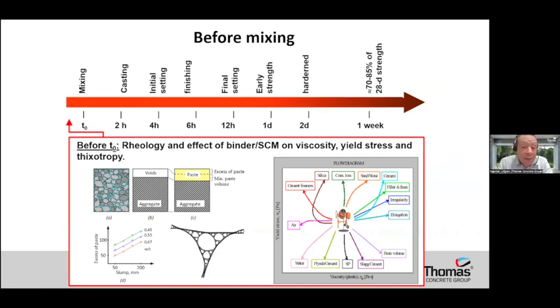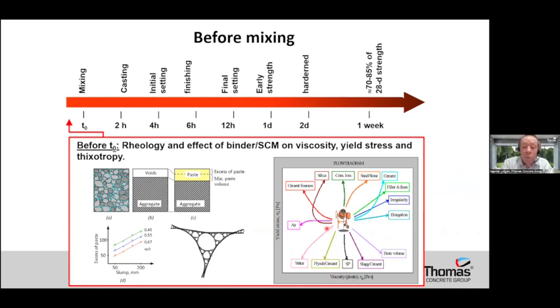So when we start looking at new mixes, the rheology and the effect of new binders on viscosity and yield stress, and also thixotropy, is extremely important. We can use materials where we work with how they influence the yield stress and viscosity. As I mentioned, fly ash and also silica fume are very good at reducing the plastic viscosity, which can be an important parameter. So knowing the materials, we can work on how to design the concrete and design it for an appropriate use.